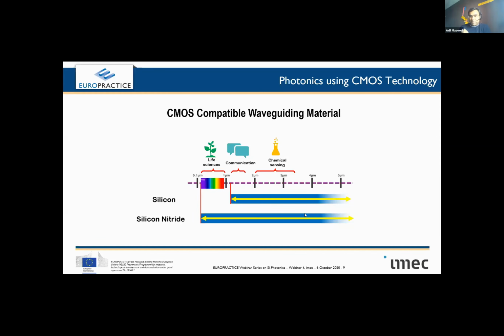First of all, if you enter into clean room, it's silicon all the way. So do not ignore that material so easily. But then again, it's the crystalline nature of silicon which gives us even more power to manipulate it. The fact that its refractive index is way higher than silicon nitride means that you can make your waveguides really compact. And then over 40, 50 years since the inception of the semiconductor industry, silicon has been treated with all sorts of tests and conditioning to do this and that. Why not use that and put it to some use? So that makes a very strong case for silicon and also for silicon nitride.